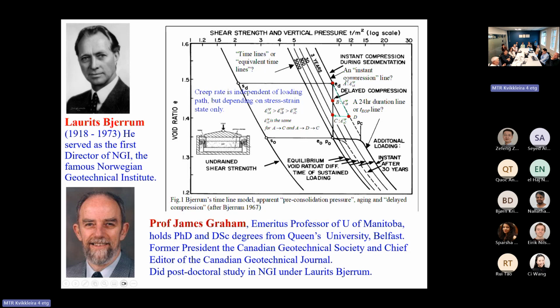This is different for each timeline. For each timeline, here, the viscoplastic strain rate can be determined. And on the same timeline, the viscoplastic strain rate is constant. Each time corresponds to a constant viscoplastic strain rate. That's one. Another thing is I can get, for example, from A, B to C, a viscoplastic strain rate, and here it gradually decreases.